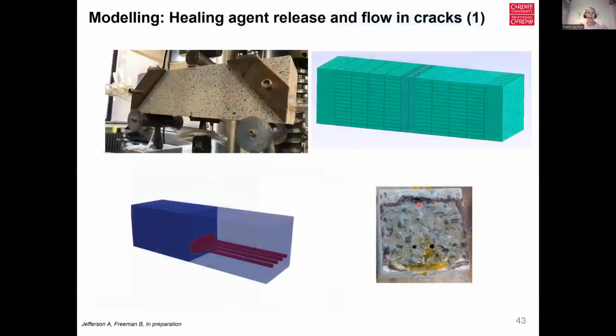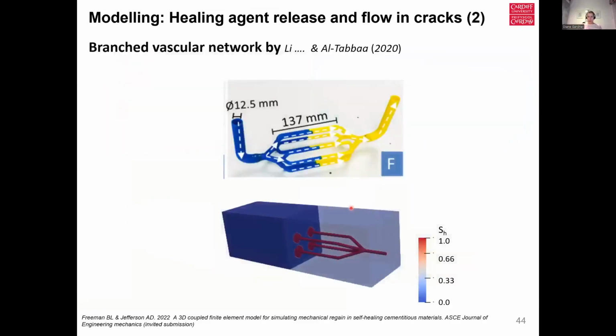We're then able to look at our beam system and set up in terms of 4 channels of network flowing in. So we get flow from our vascular network into the crack plane, such that we can see coverage of cyanoacrylate on the crack plane. We are able to extend this to some of the networks perhaps our colleagues at University of Cambridge have been looking at in terms of these branch systems. So again, having flow from our network into the crack plane and covering the crack plane.